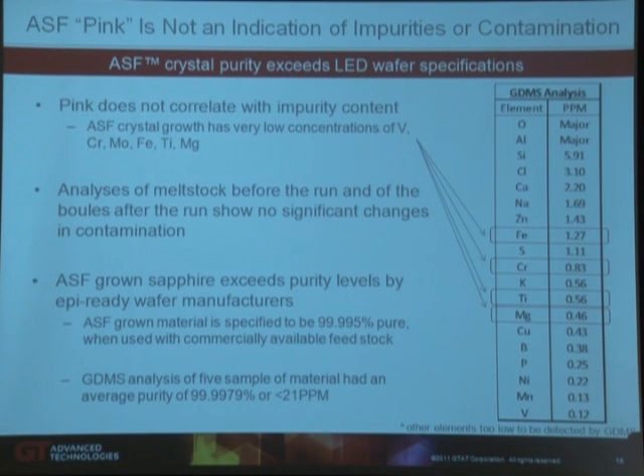The other thing we found was that ASF grown sapphire exceeds purity levels required by epi-ready wafer manufacturers, meaning most standard wafer houses, the standard for sapphire contamination is 99.995. And so in using GDMS, we analyzed a large sample of our material, and we were able to determine that the sample of material had an average purity which exceeded the 99.995, or less than 21 parts per million. And that the normal suspects that might have caused the pink color, meaning chromium, molybdenum, iron, titanium, or magnesium, were at levels that were barely detectable. So we determined that contamination was not the cause of any of the color.